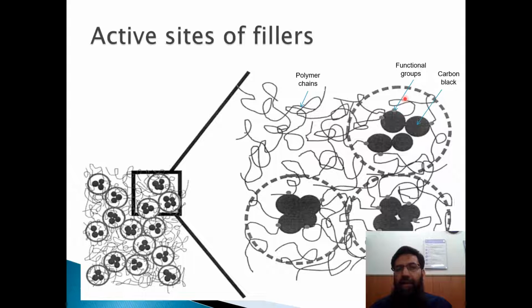So the presence of the active sites, on the one side, makes the aggregates and agglomerates of different particles, whereas on the other side, the presence of active sites is important for the interaction with the polymer chains as well. So if we have better interaction of filler with the polymer chains, we have the better reinforcement, and if we have better reinforcement, we will have the better mechanical properties of the polymer compounds. So the active sites play a major role during the compounding of the filler with the different polymers, because on one side, we need the high shear to disperse the filler in the polymer. On the other side, they would give us the better mechanical performance by the reinforcement mechanism.